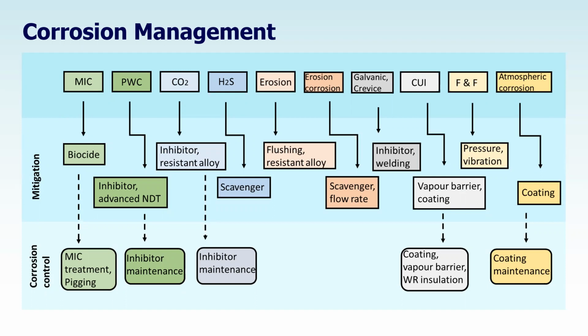Applying biocides will kill the bacteria and mitigate the microbial activities. MIC corrosion is controlled through increasing the pigging frequency and MIC treatment with a different combination of biocides. If we use a single biocide, the bacteria will become immune and stay longer. So PWC and CO2 corrosions are mitigated and controlled with a selection of suitable material with resistance and applying an inhibitor and maintaining the inhibitor availability.